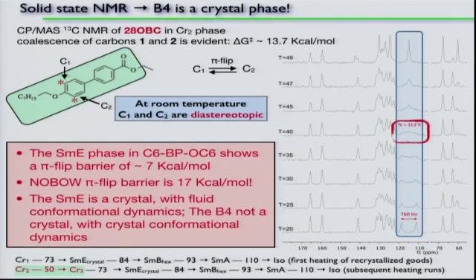Okay, it might be happening really slowly in the crystal at room temperature, but as you heat it up, it starts going faster, and you get to a point where you just see what's called coalescence. That's a quantum mechanical effect. You can no longer resolve the peaks because they're exchanging too fast, and those frequencies are too close together. Okay, and then as you keep heating it up, then it just turns into a sharp singlet, which is what you would see in solution, because that rotation is happening really fast.